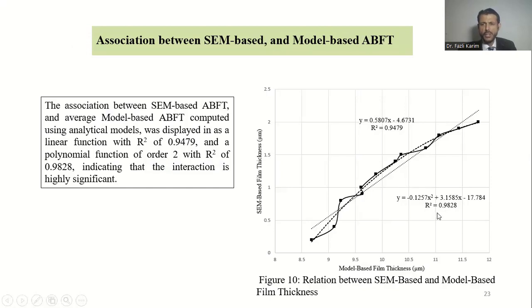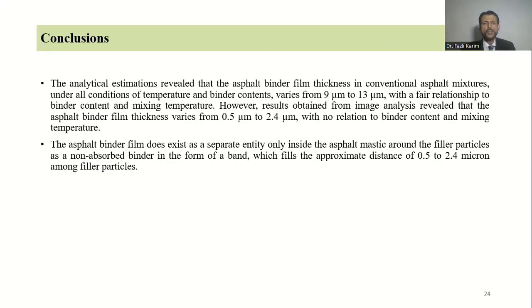So these new models have been developed, which will be used to transform the analytically assessed film thickness into the value of film thickness based on image analysis. So these are some of the findings. The analytical estimation revealed that the asphalt binder film thickness in conventional asphalt mixture under all conditions of temperature and binder content varies from 9 micrometer to 13 micrometer, with a fair relationship to binder content and mixing temperature.